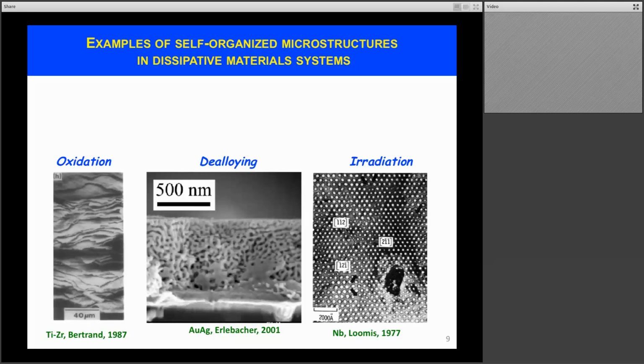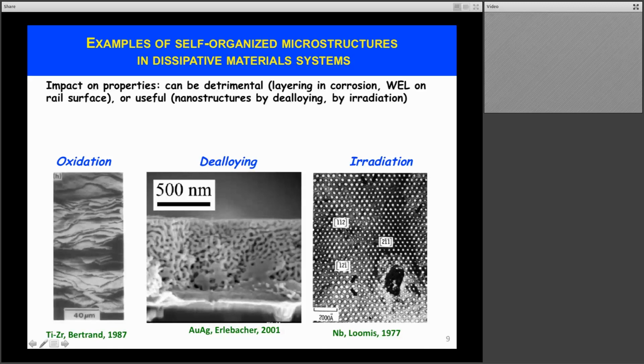And on the right-hand side also, it's another situation where, in this case, one is driving the material away from equilibrium by irradiation, and that results in the formation of this well-organized lattice of voids, but at a length scale that's larger than the crystallographic underlying lattice of, here, niobium in this case. And so these self-organization reactions can be detrimental.